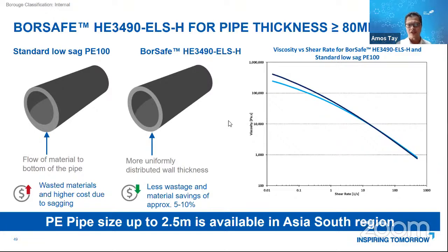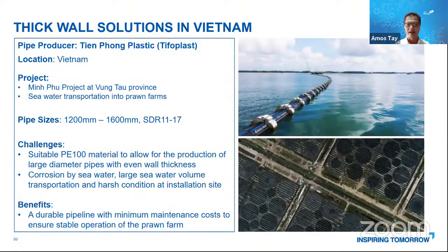It's better resistance against gravity. And then, of course, if you look further down, at the higher viscosity or rather shear rate, you see that the viscosity is similar to the standard PE100, meaning that the processing of this ELSH and the standard PE100 is similar. So there is no impact to the processing condition when you make this pipe. And by the way, the PE pipes can reach up to 2.5 meters already in Asia South.